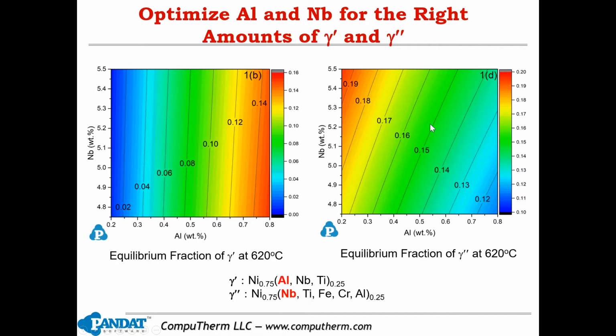And then the right figure is the fraction of gamma double prime. And as you can see, the gamma double prime takes the opposite trend. So when you increase Al content from 0.2 to 0.8%, the volume fraction decreased from 19% to 12%.